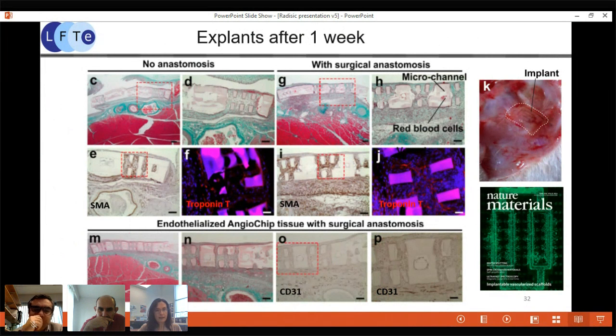You can see that if we use surgical anastomosis, these endothelial cell channels will remain open. In some cases, we did have some thrombosis, so it's not perfect. And we can see in many channels that these endothelial cells really remained on the scaffold wall, but that's really for 1 week after implantation. We can also see infiltration of smooth muscle actin-positive cells, survival of implanted cells, as demonstrated by troponin T staining.